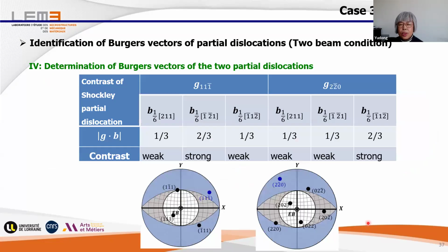And now, which kind of reflection plane should we use? Luda also did the homework. He checked a lot of reflection planes with a big table. Finally, he found these 2 are very nice. And so in this case, we use the so-called very famous g·b criteria.